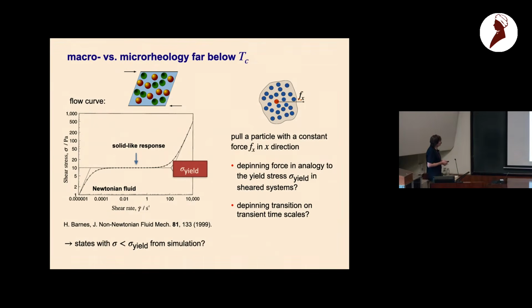macrorheology. It's a kind of proof of concept. This is a plot from this article by Barnes. This is a flow curve of a liquid far below Tc, close to the glass transition temperature. You have this plateau-like region which marks the yield stress, and then eventually at very, very low shear rates, you would expect a Newtonian fluid state. What I would like to study is, can one access such states in the simulation? To this end, we use swap Monte Carlo.